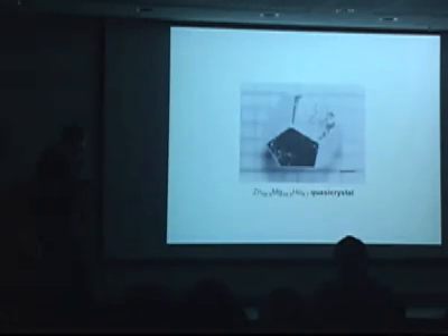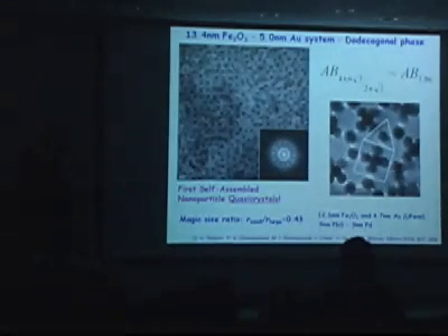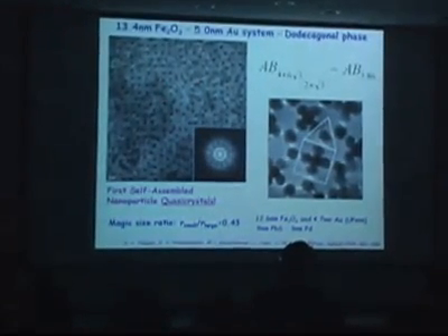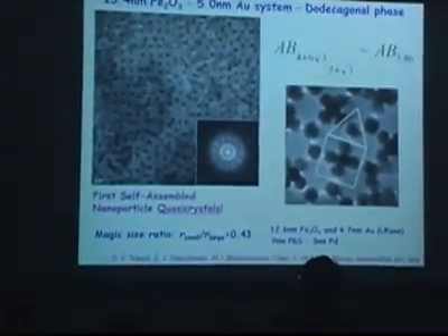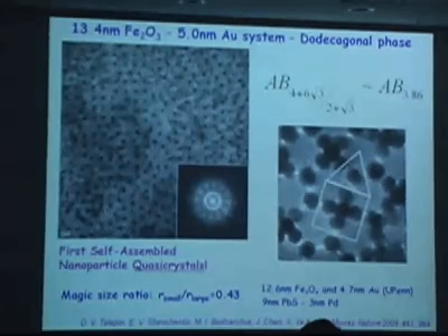But the question in the field: the first discovery of quasicrystals, aperiodic structures in an intermetallic compound, was made in 1984. So for about 25 years, there was a very important puzzle. What is the role of directional interactions in this? Because we have holmium, we have d orbitals, we have f orbitals, they form a complex network of interactions. So the question is, what are the magic forces that assemble such complex aperiodic structures? And we've shown that you don't need any magic forces. Just packing or entropic principles, or sphere packing principles, derived from particle size ratios, can be sufficient. I don't want to say that they are always dominant, but they can be sufficient to self-assemble particles into quasi-periodic patterns.